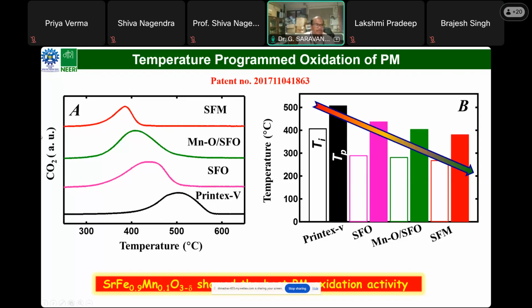Okay. So when we put manganese in the lattice of strontium ferrite, even around 300 degrees it started showing activity. So at less than 400, about 380 degrees centigrade, you can completely oxidize the particulate matter that we have used. So manganese substituted strontium ferrite has the potential to take care of diesel particulate matter oxidation.